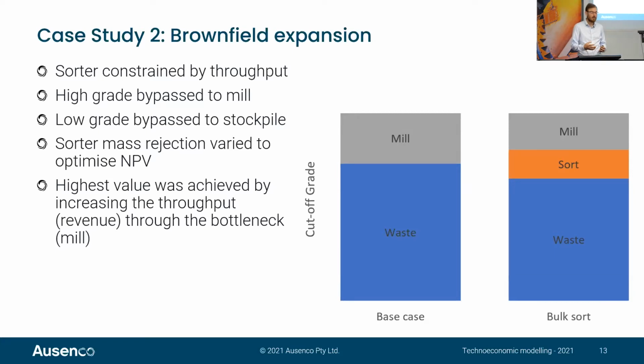So the sorter only saw that kind of marginal material, and then the mass rejection was varied to optimize NPV. So we're able to pull that into the technoeconomic modeling. And the highest value was achieved by actually increasing the throughput, the revenue through the bottleneck, which was the mill. So once again, that goes back to what we were talking about as the goal in all of this.